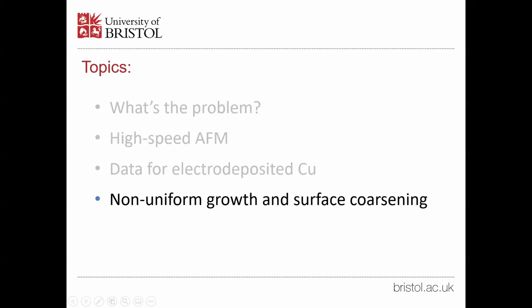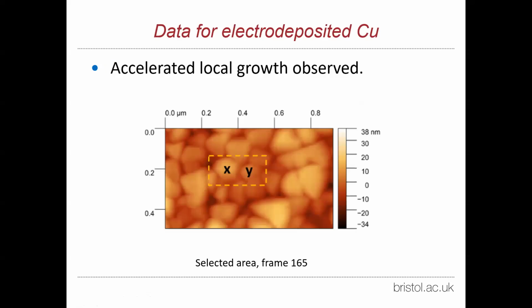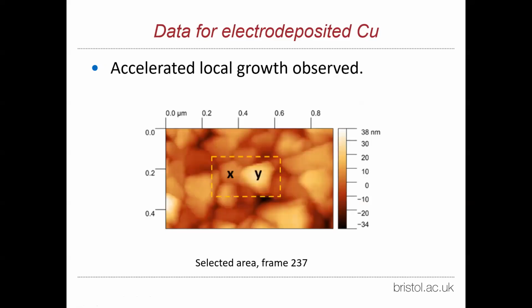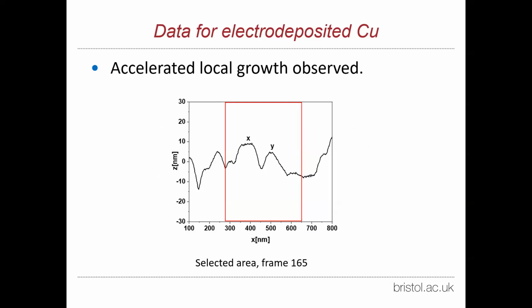So now back to some experimental data. We're interested in why the film grows non-uniformly and the surface becomes coarser. We can look at our video and select a couple of grains. Here you see two grains, X and Y, at an early stage, relatively, of growth. A little bit later, look at the grain Y. It has become much bigger than its neighbor. So this is actually, curiously enough, for such an old technique, possibly the first time that accelerated local growth has been observed. Here you see a cross section.